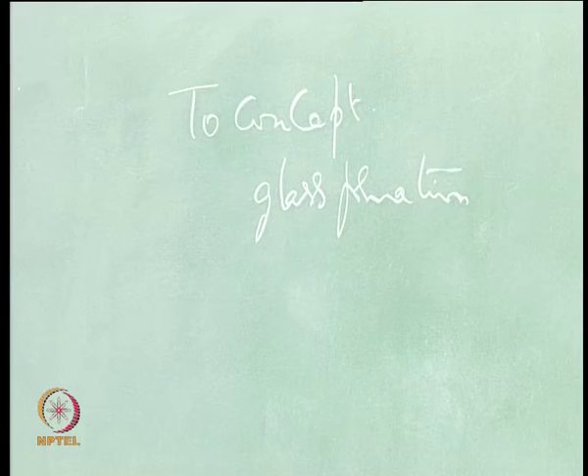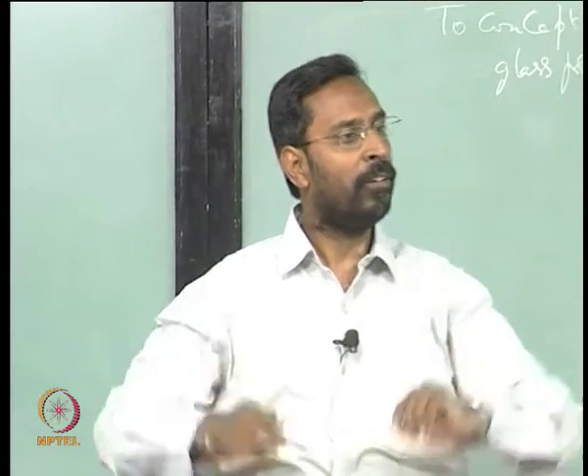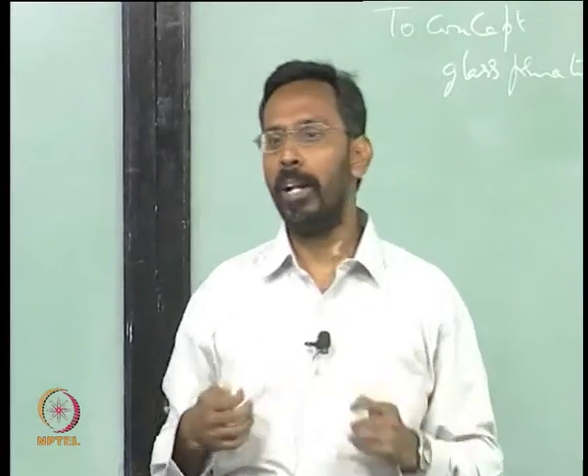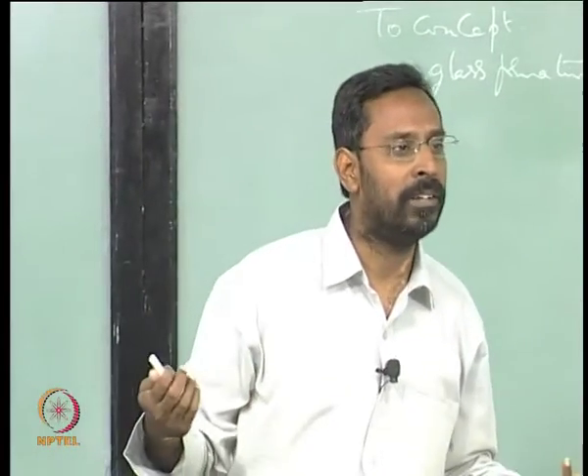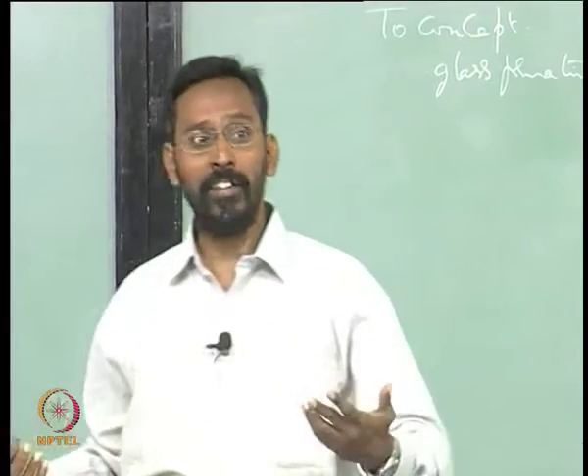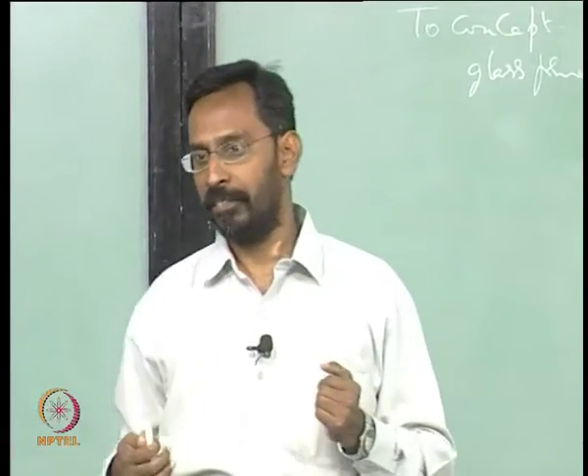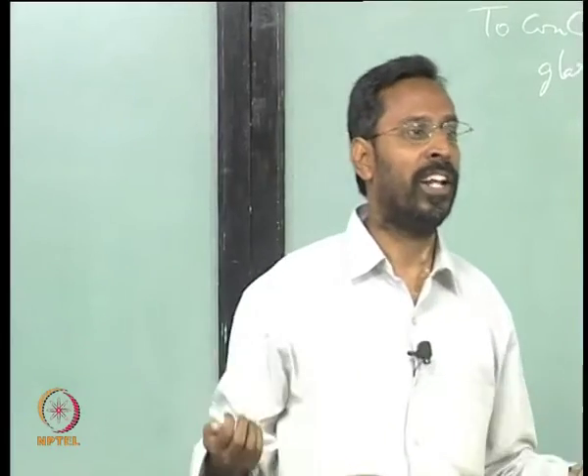Usually you see glass formation only when there are eutectics, because eutectic is where the liquid is stable. The meaning of eutectic is the melting point depression, isn't it? Many of you know eutectic means low melting. So with respect to the two pure metal melting points, the eutectic always has a lower melting point. Lower melting point basically means liquid is stable. So if the liquid is stable, then only you would get a glass. If the solid is stable, you won't get a glass.